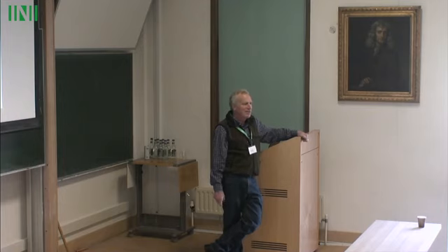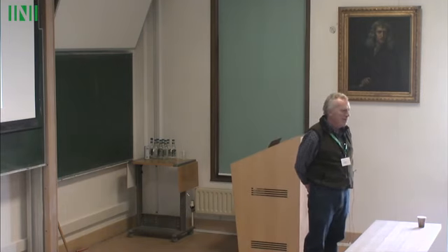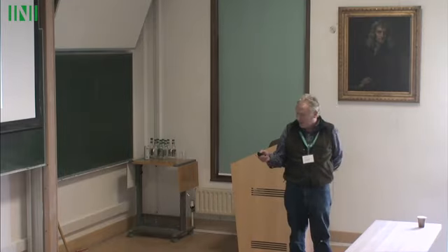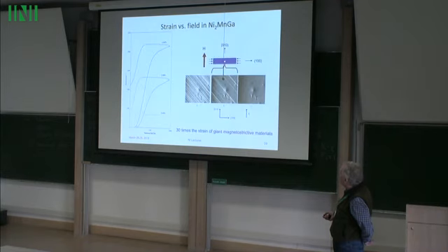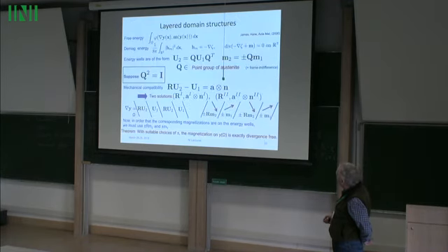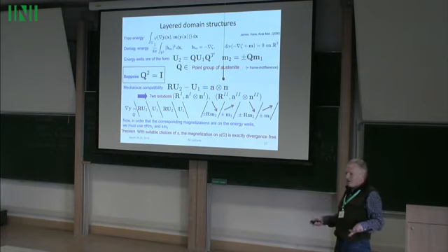So if I look at the energy, which has both magnetization and information, there is exchange there. Right. And did you try to lose it, maybe relax it, because then the problem becomes a little bit easier as far as I understand. Yes, of course, all this analysis I did, I just dropped exchange, these kinds of simple domain structures. I just simply dropped exchange, these arguments here. And these interfaces, I understand, could be smooth. I mean, these would be smoothed interfaces if you had exchange. It actually makes sense to drop exchange because, looking at the size of...